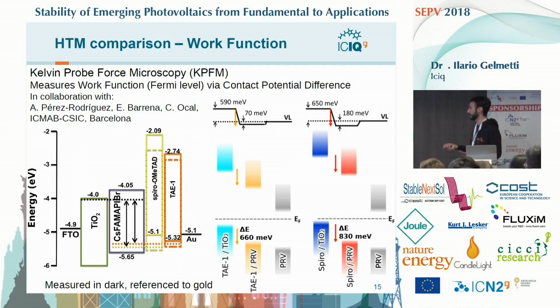So there is a bigger shift, so the spiro-OMeTAD level managed to get closer to the valence band maximum of the perovskite when layered on perovskite.